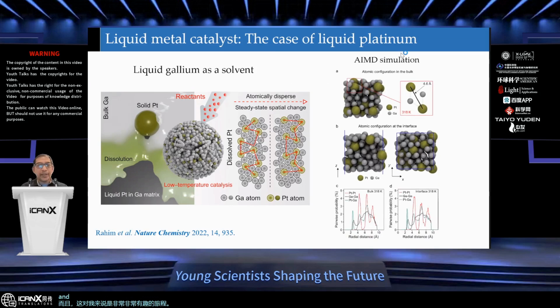And one of the characterizations that we have done by simulation, that kind of format, is now what people look at. We do some experimental characterization like XPS, XRD. You can basically check whether the dispersion of the metal that you are dissolving, the solid metal, is atomically dispersed. And of course, we have to maintain the solubility limit at a specific temperature. And then we have the simulation that confirms all these results. We do some more. But what was really fascinating, initially, I was not believing it either.